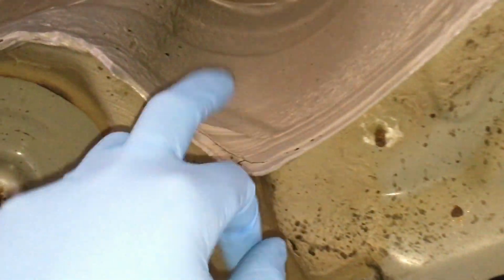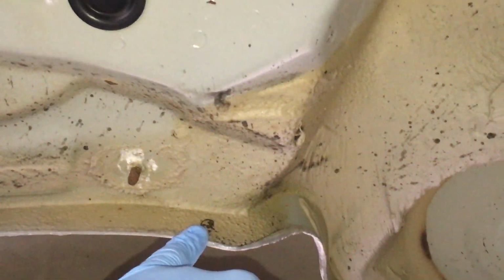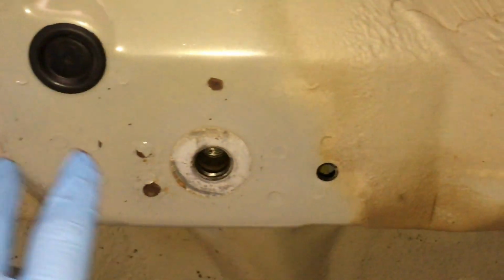Very slight split in the seam sealer edge here, which is also an indication of the rear axle carrier panel very slightly moving independently to the wheel arch panel, which it's spot welded to, exactly in the location that we've got a breakage here. Mounting points in general look good, apart from the hairline crack there. Chassis legs are appearing okay.